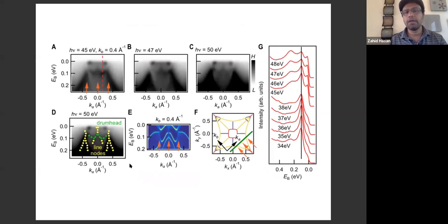So one obvious signature is that if something is a surface state and you scan the kz direction in your ARPES spectrometer, then things will not move, because a two-dimensional object doesn't disperse in the third dimension. So kz dispersion would be zero, or nearly zero. This is what we see. That's how we figured out that these line nodes are on the surface, they connect as drumhead states. And drumhead states are, so we start to map that stuff.